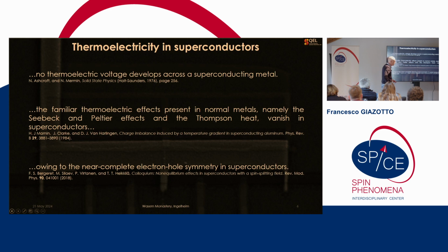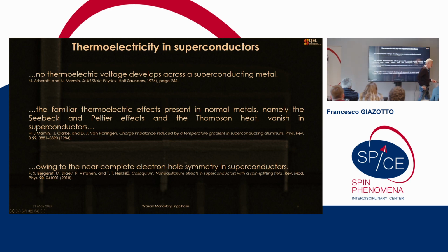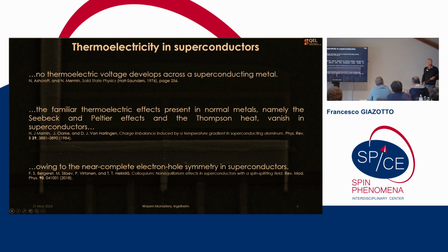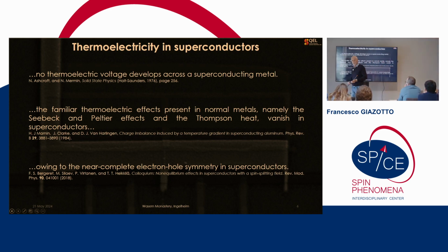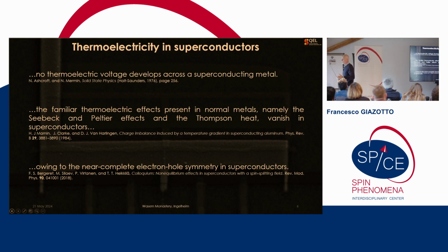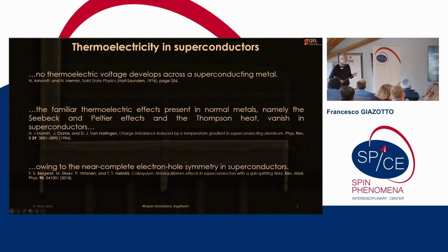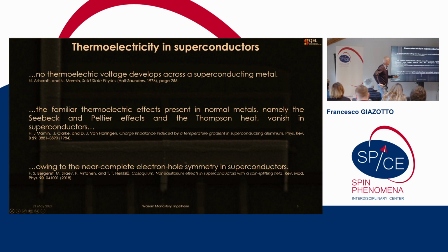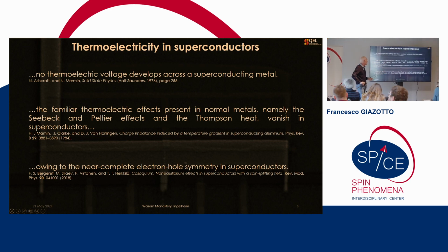This stems from the nearly perfect electron-hole symmetry which exists in conventional superconductors. Of course, in more specific superconductors like ferromagnetic or spin-split superconductors, if there is an external action to break the electron-hole symmetry, they will provide a thermoelectric response. But in the absence of that, they are very symmetric, okay?